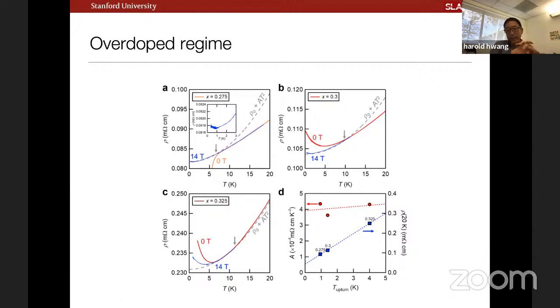But you're right, there are many open questions. I think that, for these samples, we felt confident by a number of checks that they're kind of robust. I think the other challenge for us is that as we go to higher and higher hole doping, what becomes difficult to stabilize is the perovskite phase. And what I mean by that is, let's say we wanted to do x equals 0.5. That needs nominally nickel 3.5 plus starting, and then we reduce it down. So again, this whole game is about where chemistry allows us to play, right?